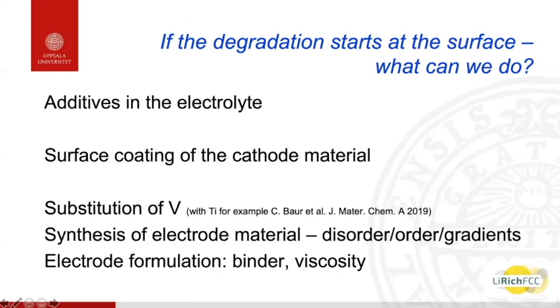So if the degradation starts at the surface, what can we do? We can have additives in the electrolyte, we can have surface coating, and we can substitute part of the vanadium with some other metal. Of course, we are testing all these things all the time. Also, can we systemize this into a more screening situation, like in Battery 2030+, so we can move faster with this kind of material or discard them. But if you really want to know what's going on at the interface, you have to develop new methods. And this is